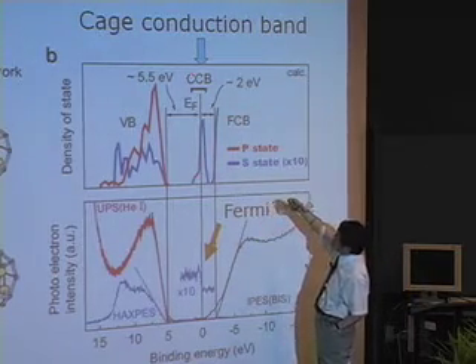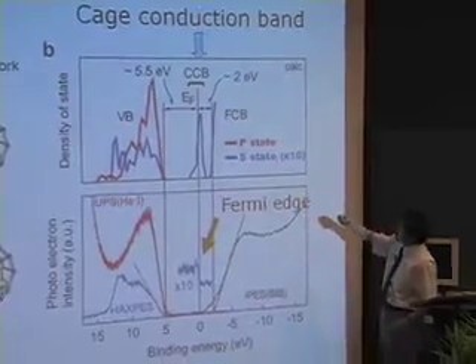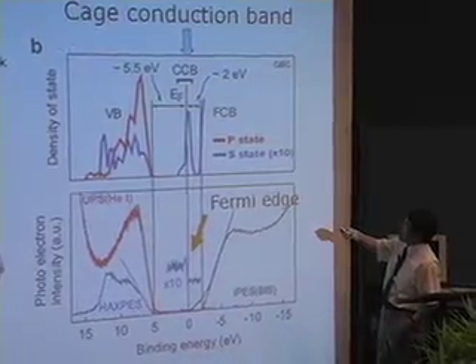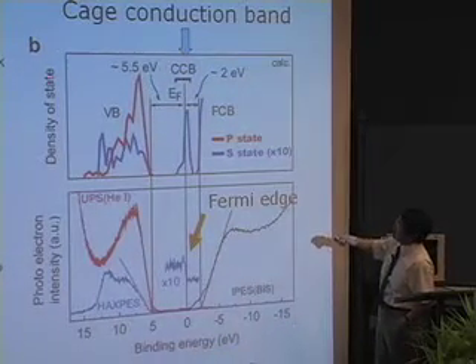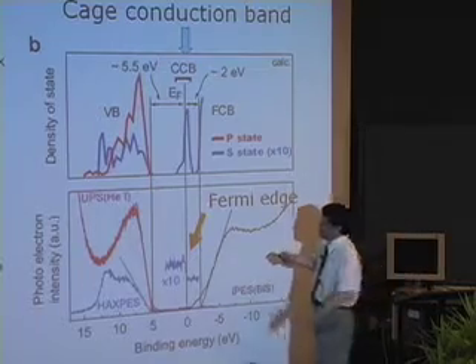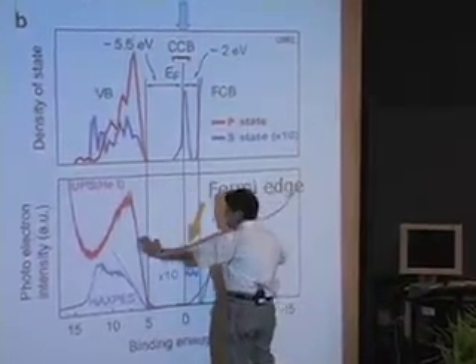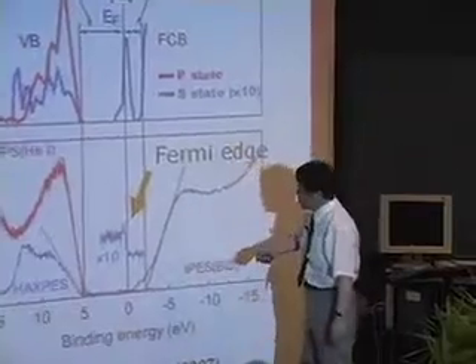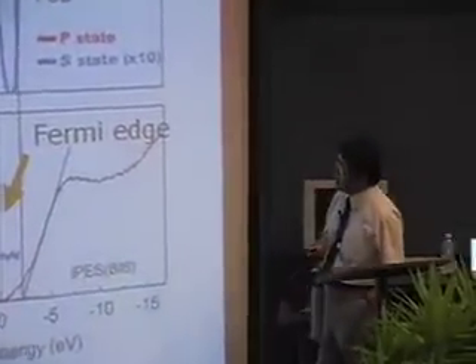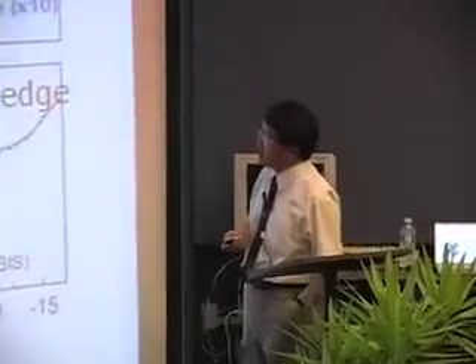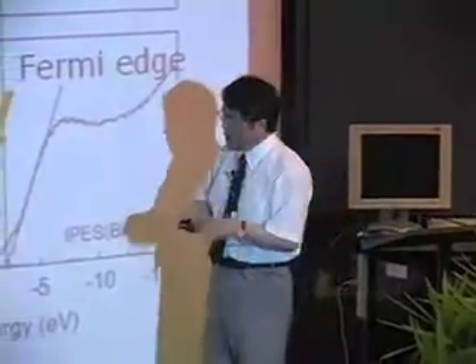This band is the cage conduction band, and this is reproduced by DFT calculations. But the problem is the calculation versus experiment - this is the data obtained by photoemission, which is pretty sensitive to the surface.